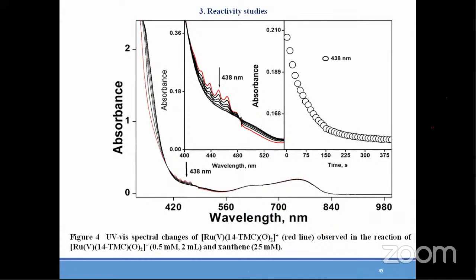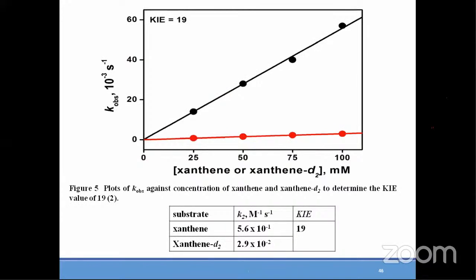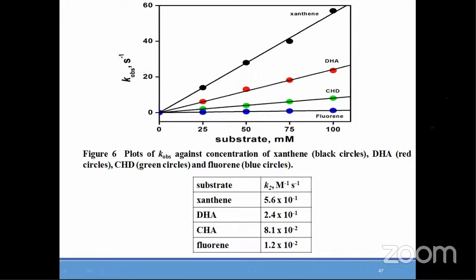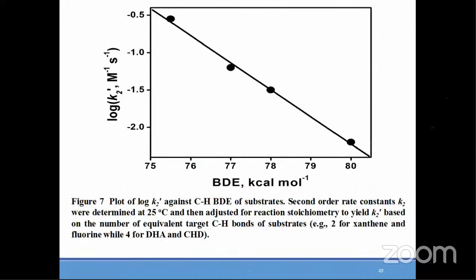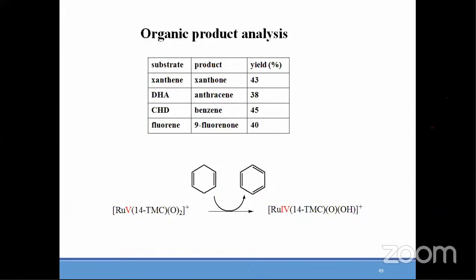Since that was an intermediate, we did some C-H activation reactions. Results you can see here. That intermediate was reacting very nicely. You can see here the band decreases with a pseudo first order rate constant. And then we could do that for xanthene, like earlier cases, so we got a large KIE value, and then we also did it with other substrates. These are the second order rate constants for them. And then we plotted the bond dissociation energy against the log k2 values. We got this, which suggests that hydrogen atom abstraction is the rate determining step in this case.